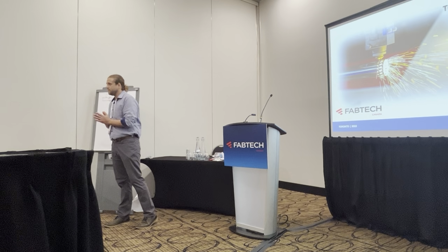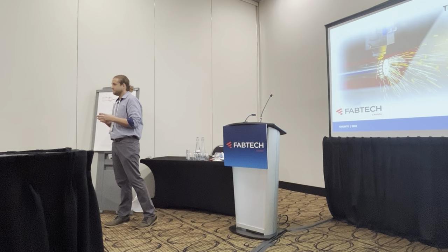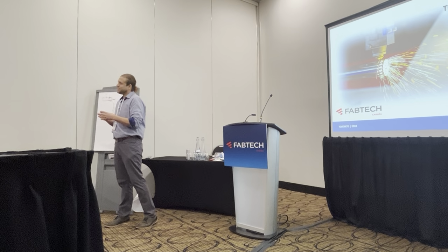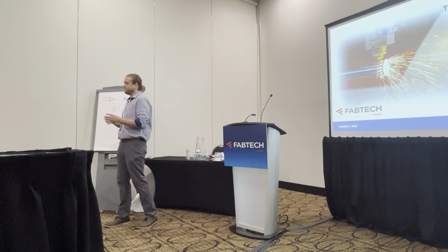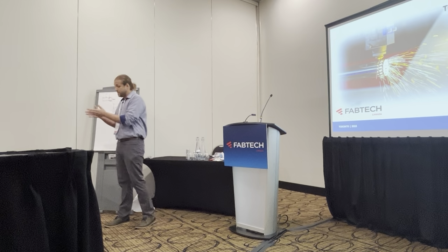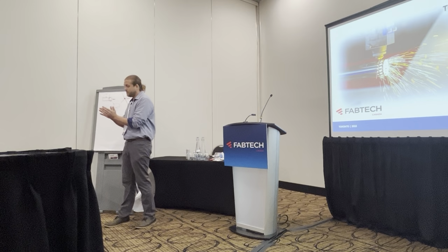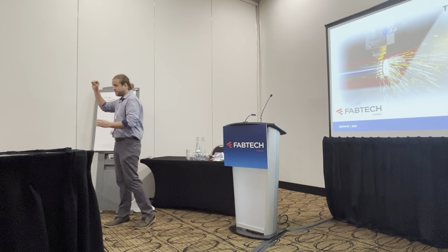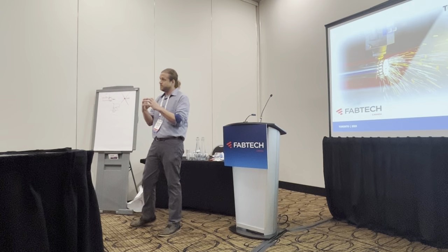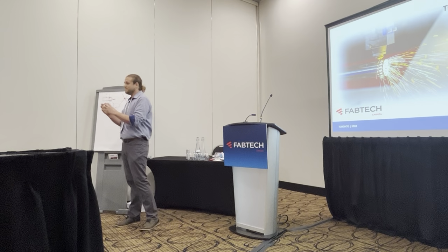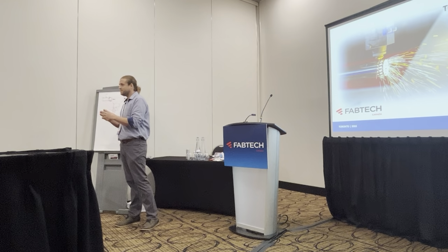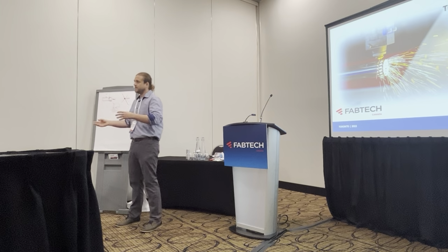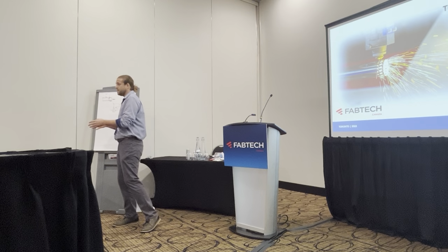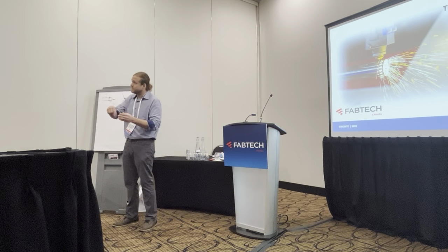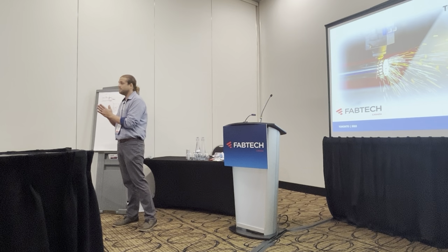What material thicknesses do you foresee yourself dealing with? I'm new to the industry. Okay, so this is just standard. That's difficult, because CO2 is going to be great for your thicker materials, and as you increase your thickness, that fiber laser is going to slow down to that CO2 speed. As you get to that quarter inch and above, now your CO2 and fiber are closer. Now your fiber rapids and its rapid movements on clamping and all that may have that advantage, but the actual cut speed is almost spot on the same.